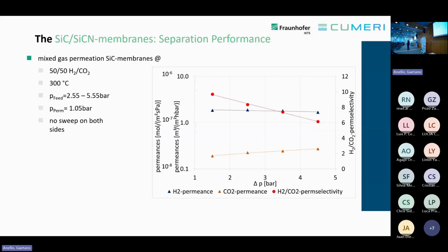Therefore, we also made mixed gas permeation tests with this kind of membrane. We mixed hydrogen and CO2 50-50, and then we proceeded with the test at 300 degrees C. We varied the feed pressure between 2.5 and 5.5 bar. Permeate pressure was kept at 1 bar, and we didn't use any sweep. And as you can see, in all conditions, in all transmembrane pressure differences, we always got a much higher hydrogen flux than CO2 flux.